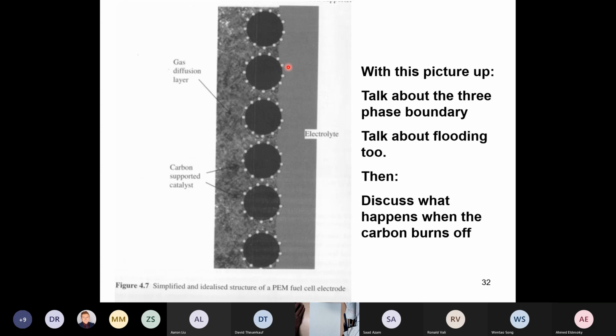Right. Now imagine that where the catalyst particle is touching the carbon, that carbon is slowly burning away. Like I was showing you, it's making CO2 because of the reaction between the oxygen and the catalyst particle. So as the carbon burns away, you lose electric contact to the catalyst. And once you lose electronic contact to the catalyst, you can't have the proton and electron and oxygen in the same place at the same time anymore to make water. So if you have carbon burn-off happening, it's a bad thing in a fuel cell. So on the air side, if you have carbon burn-off occurring, the fuel cell performance will just drop like a stone.